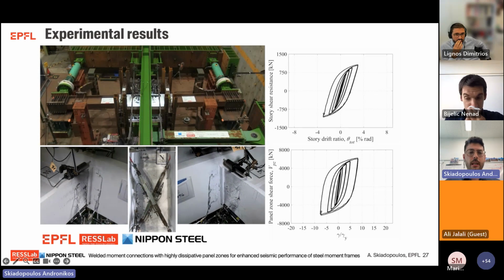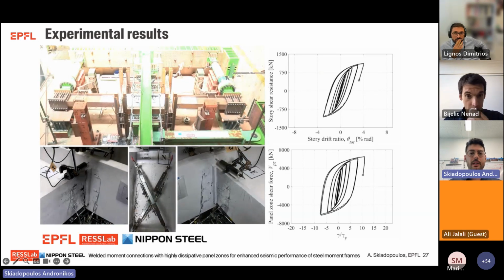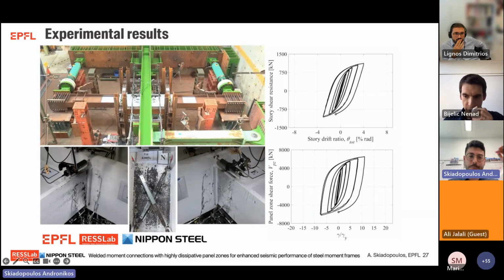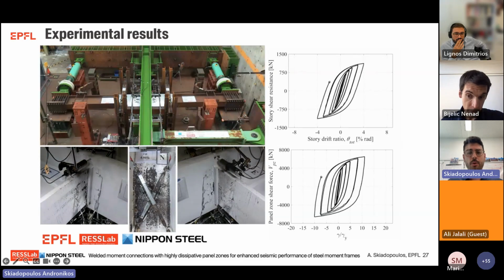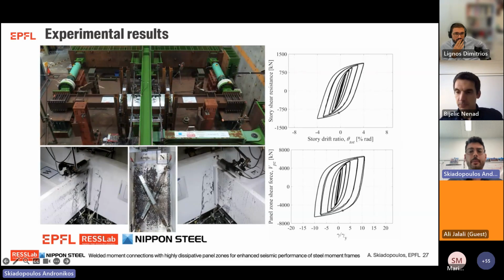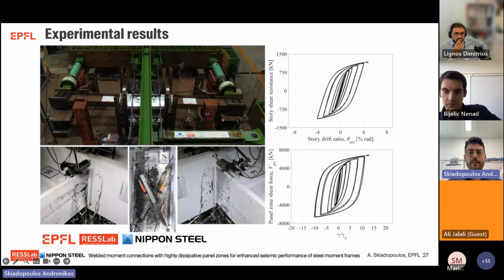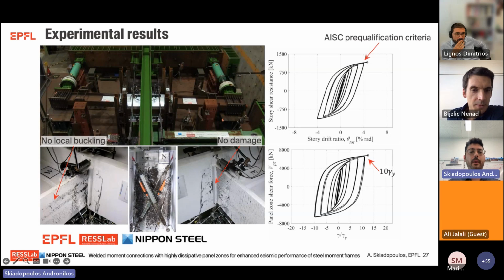Moving forward to higher lateral drift demands, at 4% story drift ratio, representative of a maximum considered earthquake event with a return period of 2,475 years, there was no incidence of beam local buckling, and there was also no damage in the proposed bevel backing bars. The panel zones reached 10 times the panel zone shear distortion at yield, which is more than the target we reached for the experimental program.